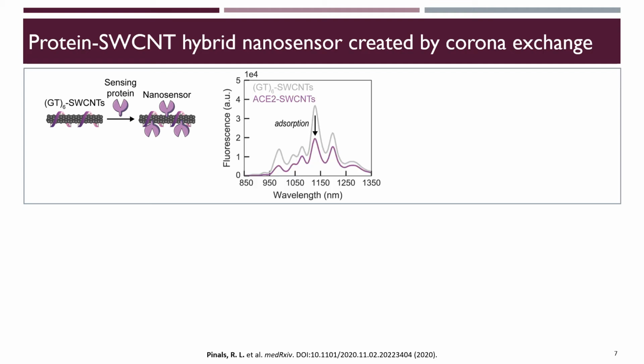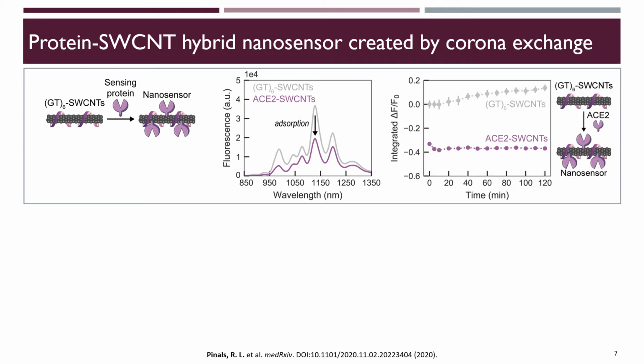Here I'm showing the resulting near-infrared fluorescence spectra, where adsorption of ACE2 onto the carbon nanotube quenches the carbon nanotube fluorescence. This quenching response levels out to about -40%, and this is an extremely time-stable construct with adsorbed ACE2, which is desirable such that our nanosensor baseline is constant.